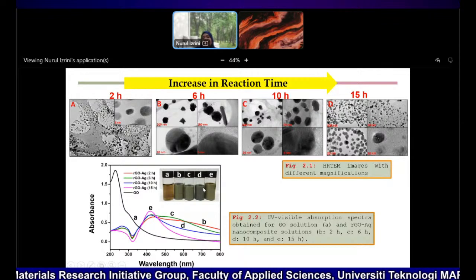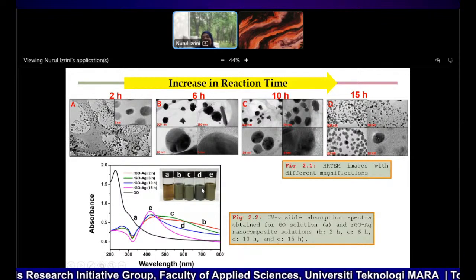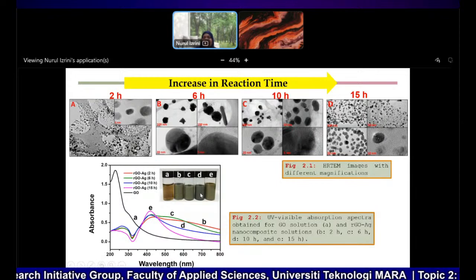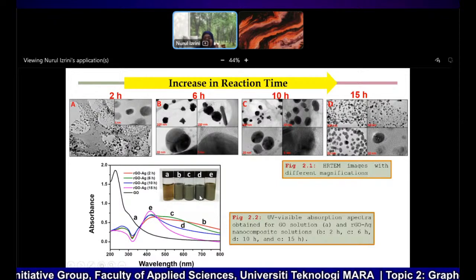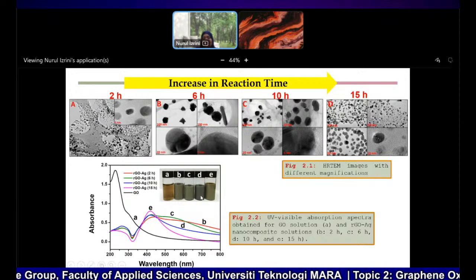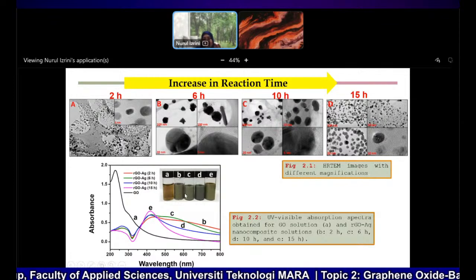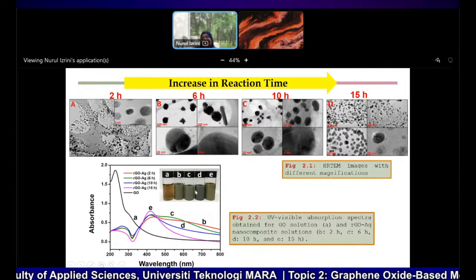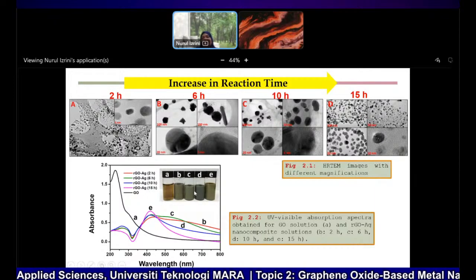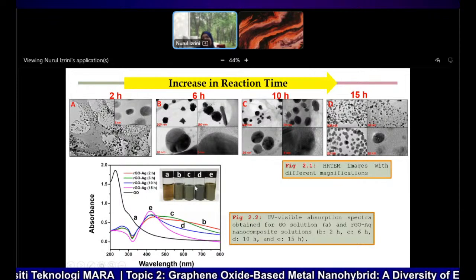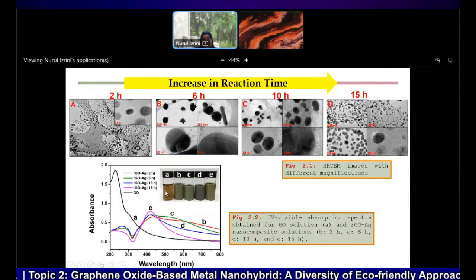So first of all, when we run the reaction, in order to confirm that our samples can form nanoparticles, based on our naked eye we can see the color change. If the color changes, the different color change gives us information that our sample successfully formed the nanoparticles. However, we still need to confirm using TEM, because we want to see what size that type of nanoparticle is, and a large population.